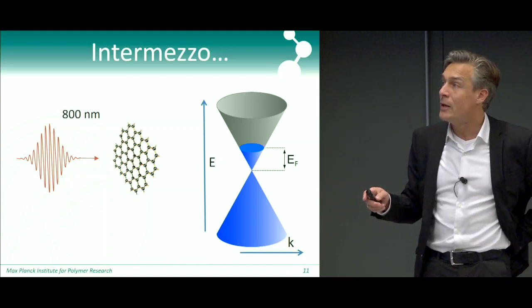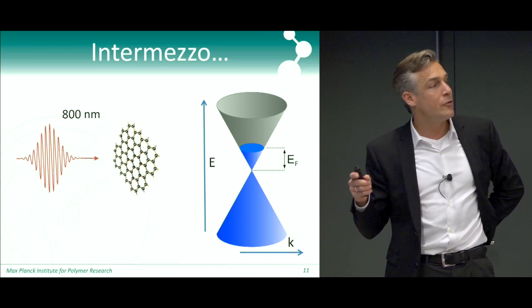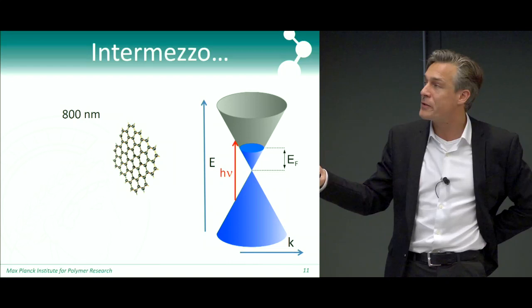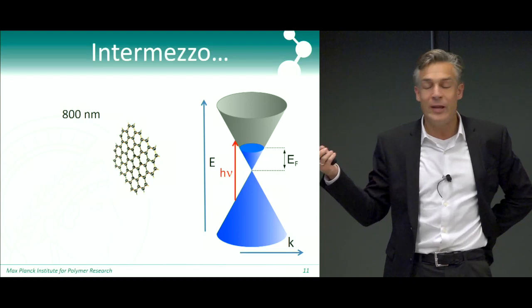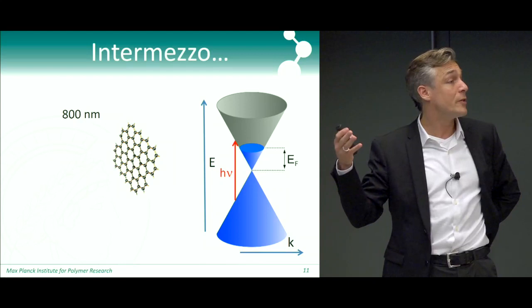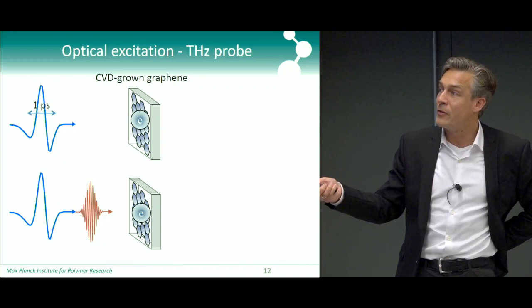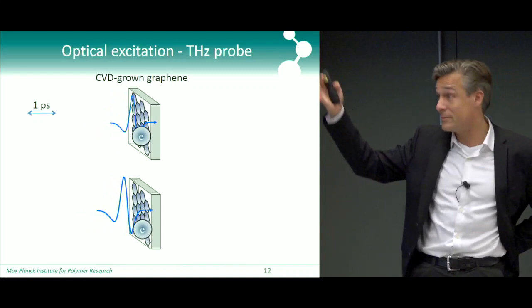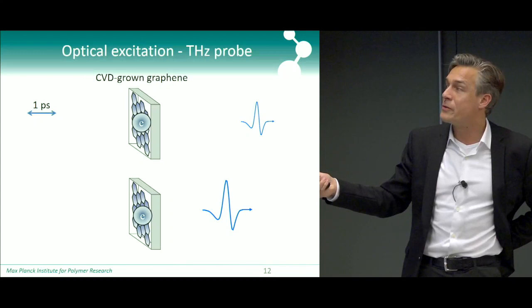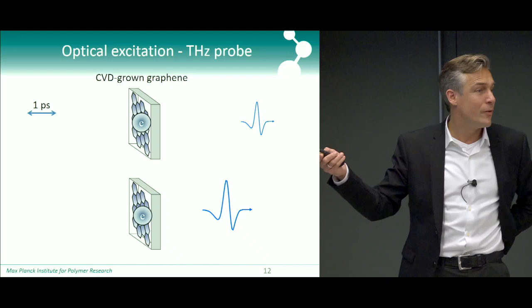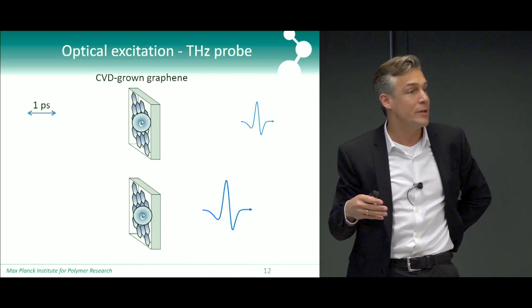We wanted to measure the photo-conductivity. The naive idea was that photo-exciting graphene would generate additional free carriers and increase the conductivity, as in any semiconductor. We were very surprised: when we compared the photo-excited case with the non-excited case, we saw more terahertz light coming through the excited graphene than through the unexcited graphene — a lowering of conductivity upon photo-excitation. This is negative photo-conductivity.